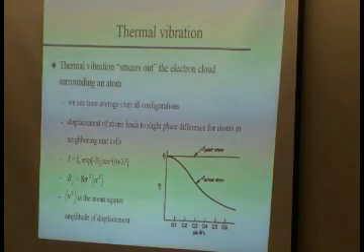There's an equation that describes it. So your F for your atom should really be an F0 times this factor, which describes the thermal vibration: e to the minus B_j sine squared theta over lambda squared. So there's your dependence on angle. And this B is actually 8 pi squared times u squared, where u squared is the mean square amplitude of displacement. So this is a direct measure of how much those atoms move.